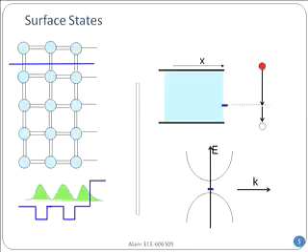Now, what is going to happen is that through those levels, an electron from the conduction band will be able to jump to the valence band with the help of these trap levels or surface states. Now, this is not a physical state in the sense of a trap level, but of course it functions as if it was one. So we have one at a given energy, and where is it? That depends on where the surface is terminated. That determines it.